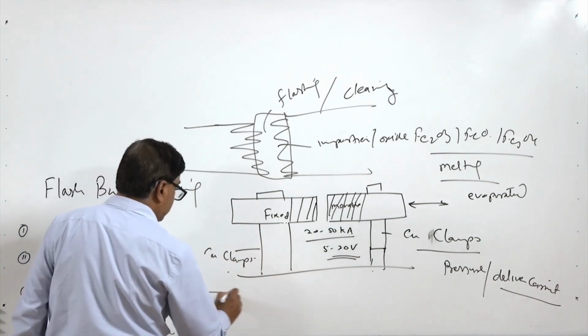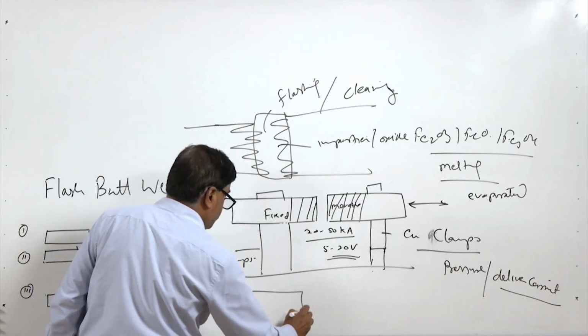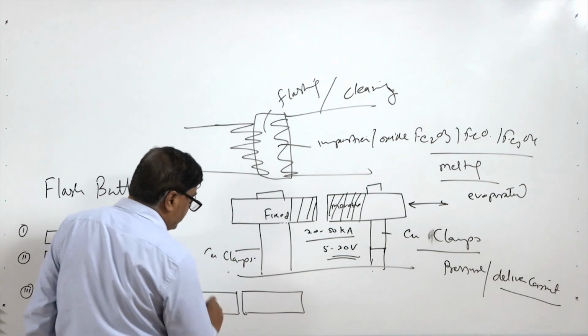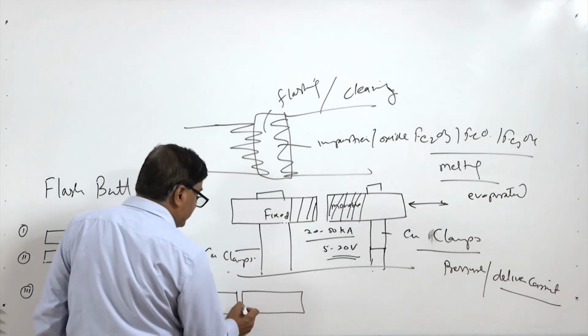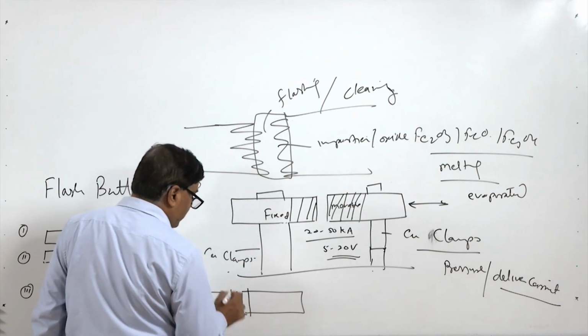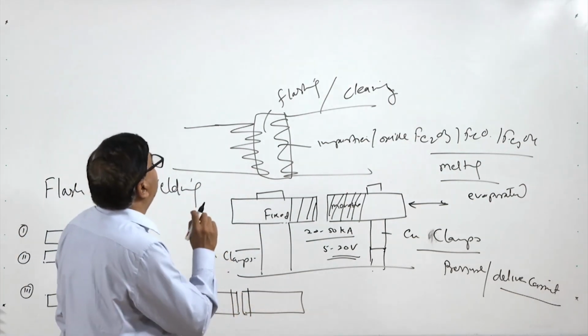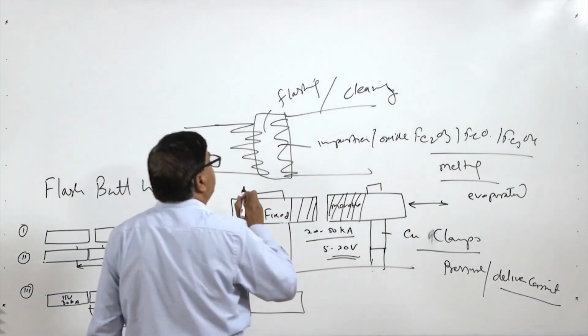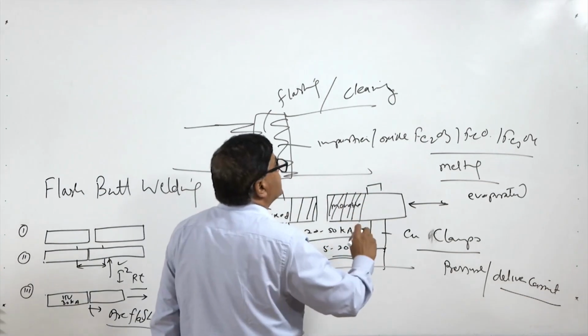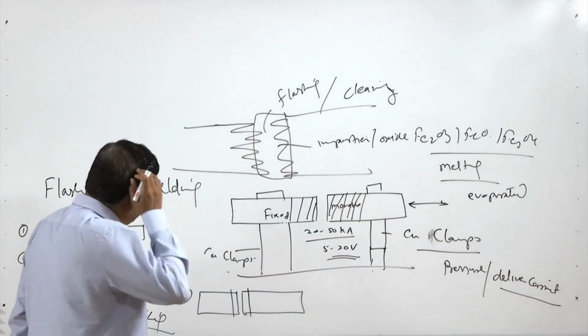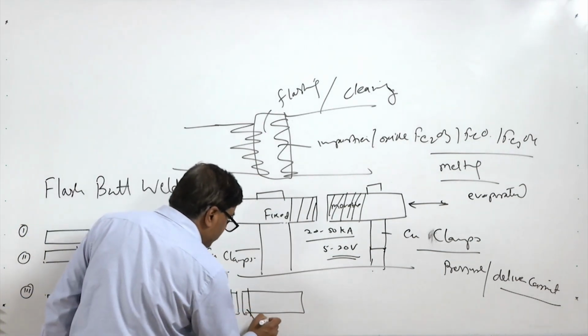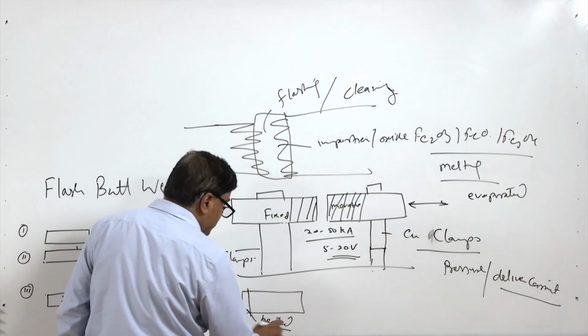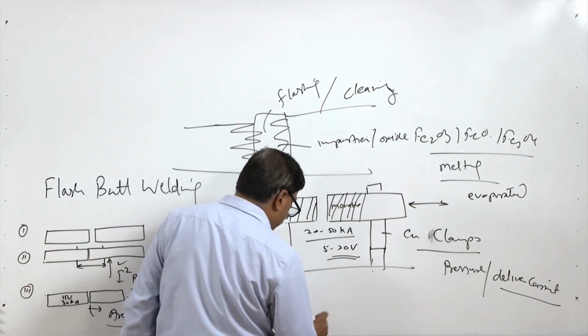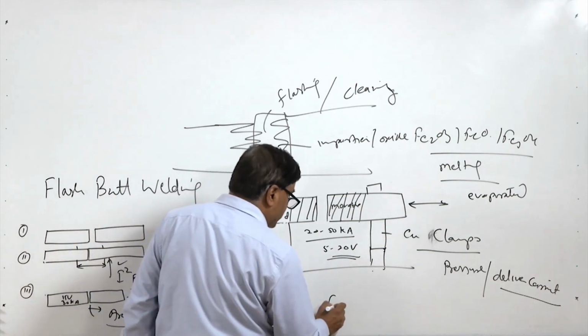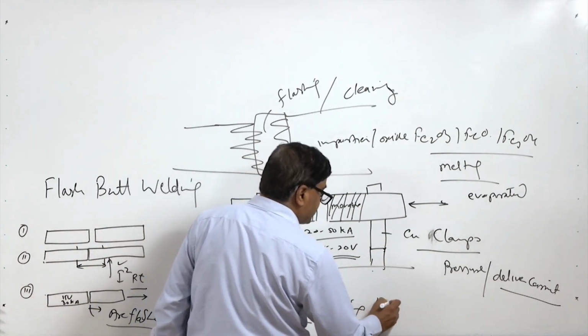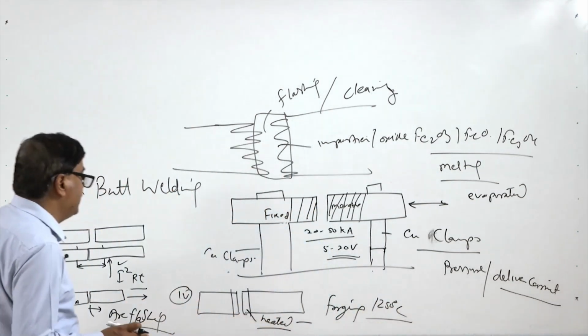Once this flashing is over, in the fourth stage the component is prepared for joining. During this period there will be a rise in temperature due to the flashing and arcing. There will be heat generation due to which impurities, oxides, etc. will be evaporated or melted. At the same time the ends will also be heated, and this will continue until the ends reach the forging temperature, say in case of steels 1250 degrees centigrade.